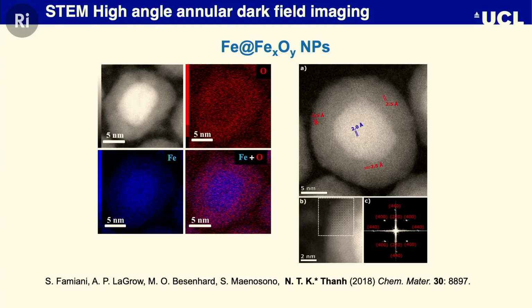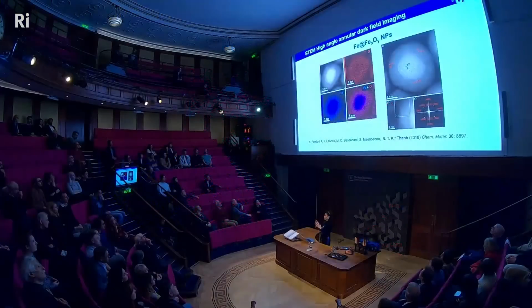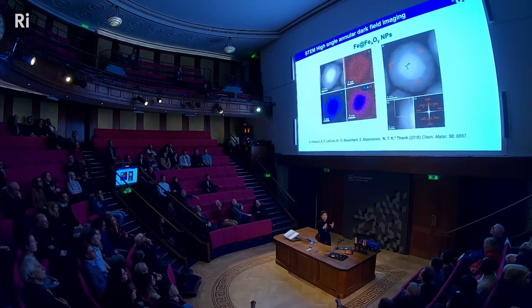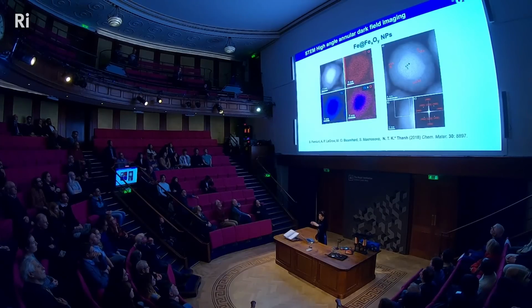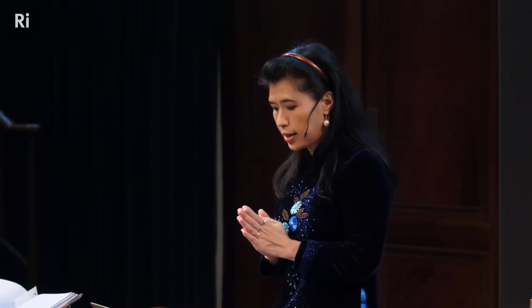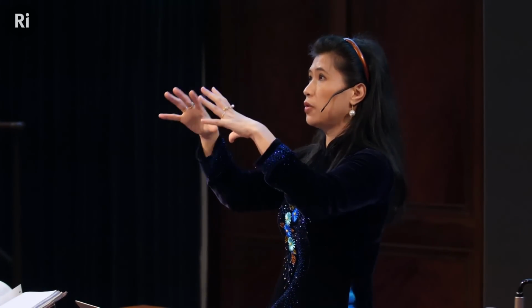So here we control the synthesis so that we make the iron oxide layer in a controlled manner. Because what we observe is that it doesn't matter what size of iron nanoparticle, the techniques are the same. So we increase the core, and then we could have a higher magnetic moment of the iron oxide core-shell structure. And you can see the white one there, how it looks on the TEM, you already see the core-shell structure.